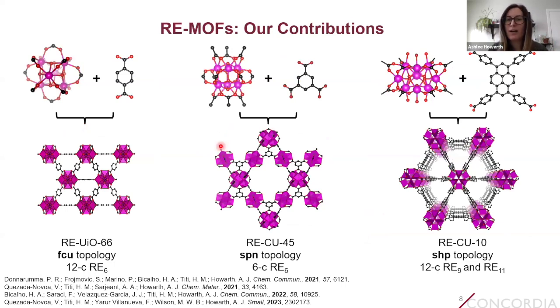So this slide summarizes our contributions to the field of rare earth cluster-based MOFs over the last 4 years or so, where we've shown that you can make rare earth analogs of a well-known zirconium-based MOF called UiO-66. And so the rare earth analogs, much like the zirconium ones, are comprised of 12-connected hexanuclear clusters bridged by these benzene dicarboxylate linkers. And the framework has the overall fcu topology.